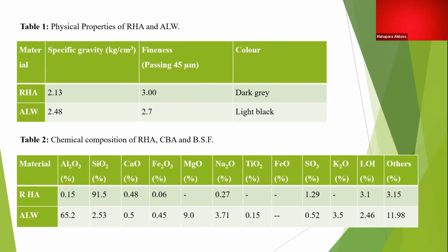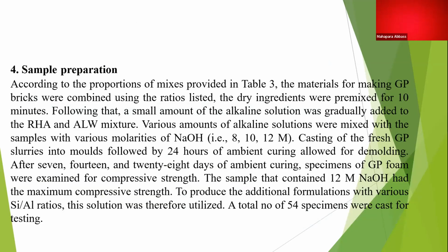For the production of geopolymer concrete, what we need is alumina and silica. In conventional, ordinary concrete, calcium silicate hydrate gel, CSH gel, is produced, which hydrates the cement and makes the bonding between the aggregates and the cement paste. But in geopolymer concrete, the formation of aluminosilicate hydrate gel is the main backbone in the polymerization, which binds the aggregate and source material together. Here we are not providing any kind of binding material, except rice husk ash, aluminum slag, and alkaline activators.